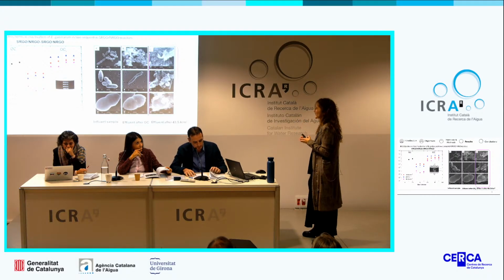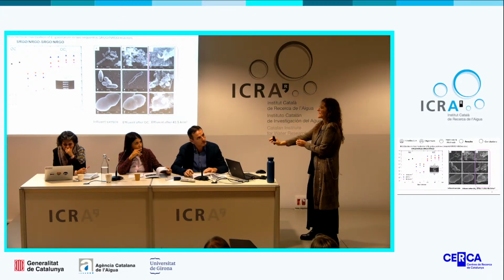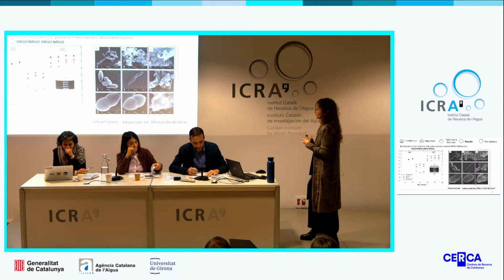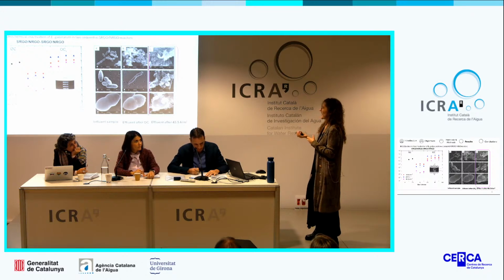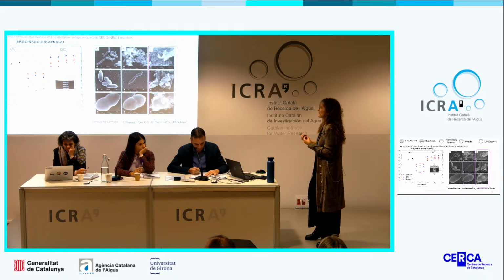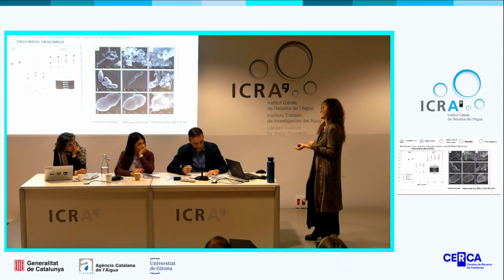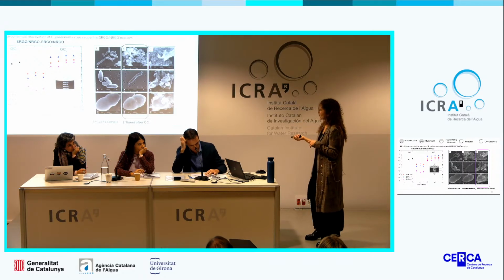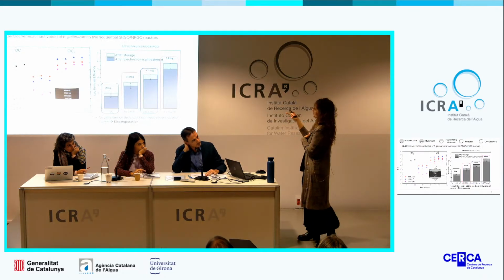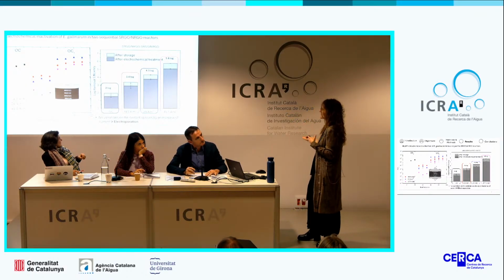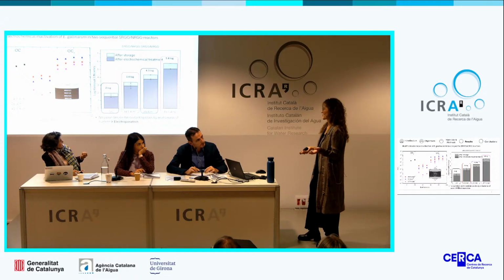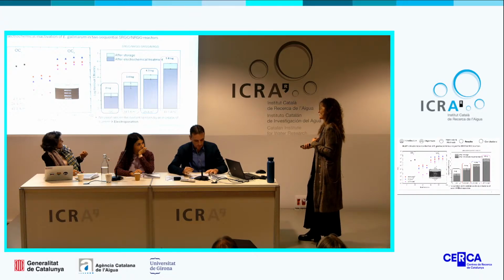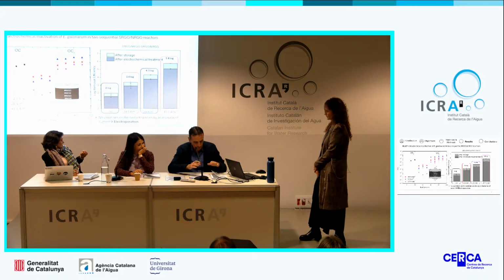Probably, but in this case, I think it's more related to the electric field not being enough to create these pores on the bacteria, because, as I mentioned during this explanation, typical electroporation treatments usually require really high potential gradients, and are directly dependent on the potential gradient. So probably if we are not applying enough potential, we are not able to inactivate all the bacteria. But regarding the oxidant species, we were determining the different oxidant species, and the variations were not that significant. So that's why we think the primary mechanism is electroporation rather than oxidant species. Okay. That's what I have concluded. So electroporation is for you the prevailing mechanism.